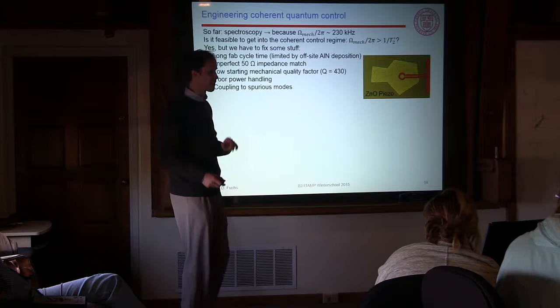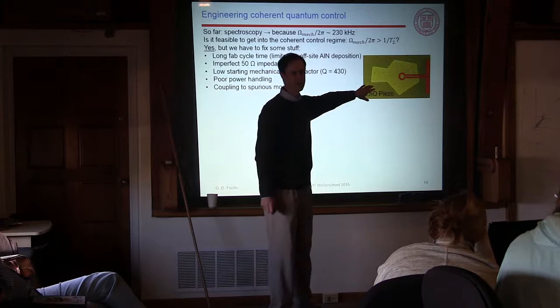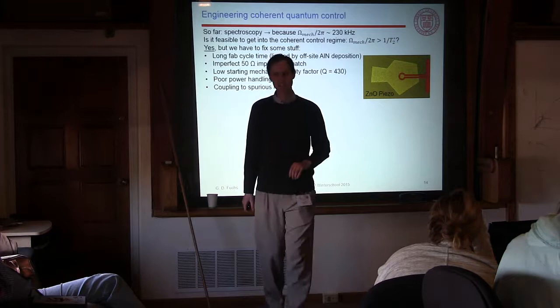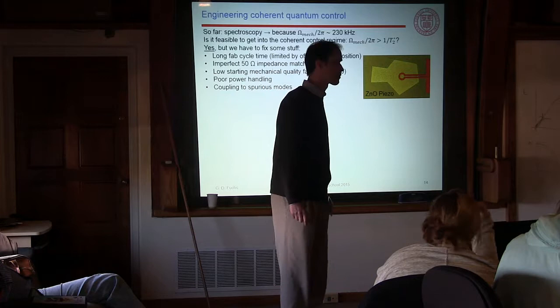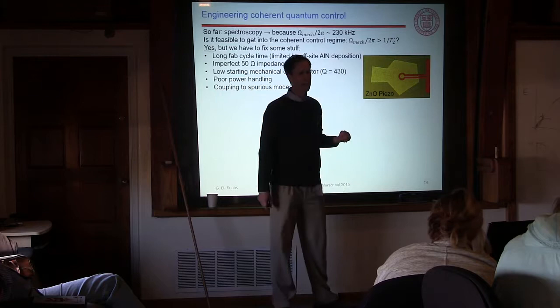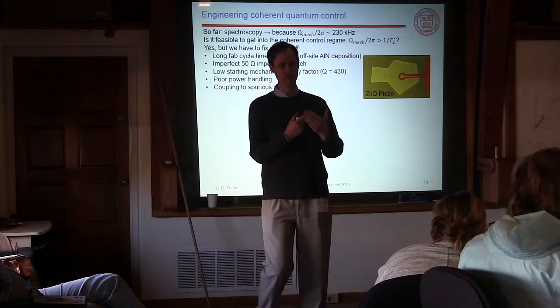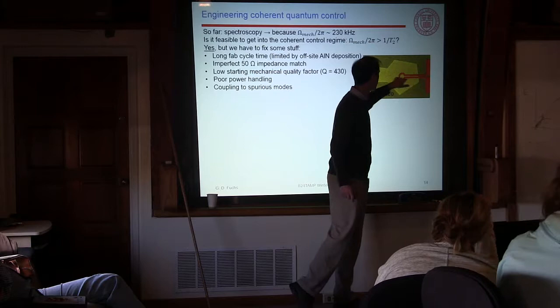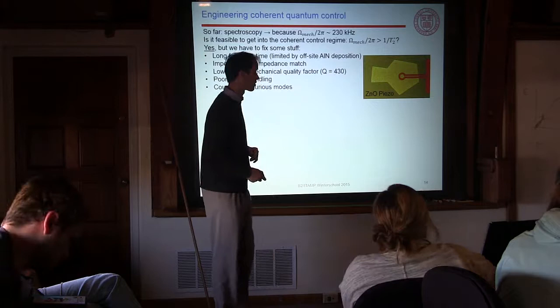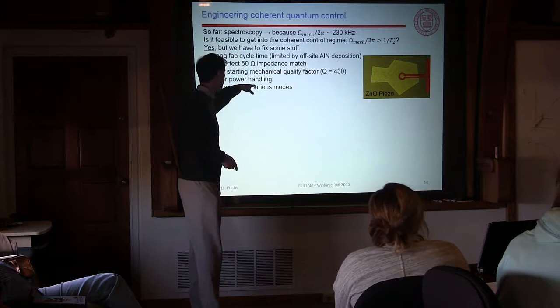Here is a microscope image of the new generation devices. The piezoelectric material is now zinc oxide, which we can deposit on-site by sputtering in an afternoon — it has the same efficiency as foundry-deposited aluminum nitride. Following Sunil's suggestion, we apodized the transducer shape to limit coupling to transverse modes, selecting more purely for the thickness mode. We also changed the shape and symmetry of the magnetic antenna on the backside, which changes the boundary condition and likely improved the Q factor.